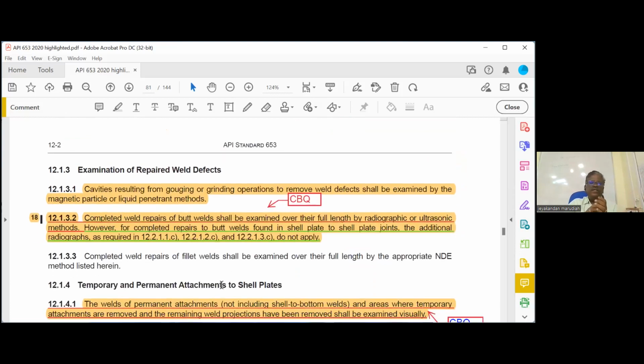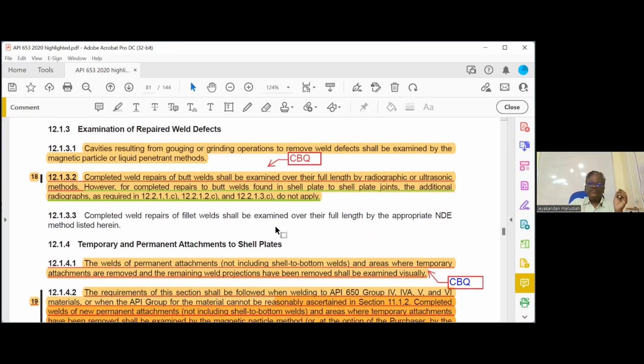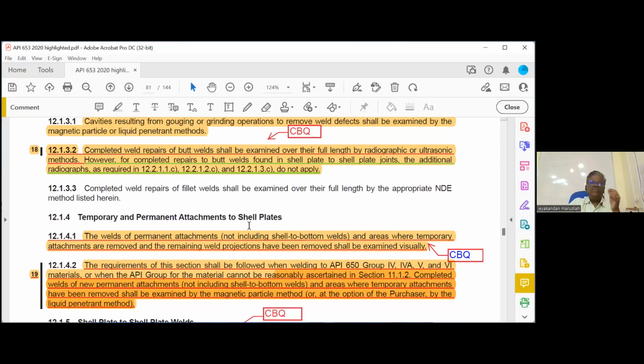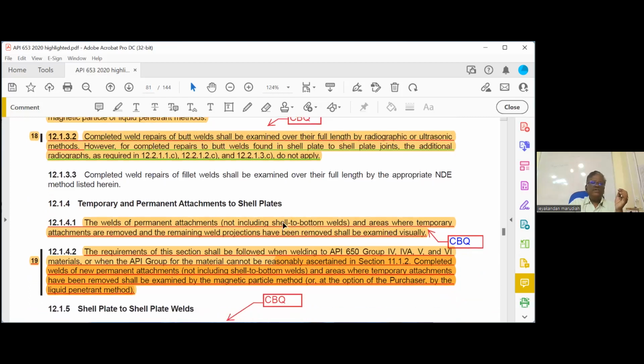Now, examination of repaired weld defects. Suppose you are making some weld repair. Completed weld repairs of butt weld shall be examined over their full length by radiography or ultrasonic, that is closed book. If you are making any weld repairs, that area completely we have to take radiograph. Then temporary or permanent attachments to shell plates. The welds of permanent attachments and the areas where temporary attachments are removed and the remaining weld portions have been removed shall be examined visually. We have to check visually.